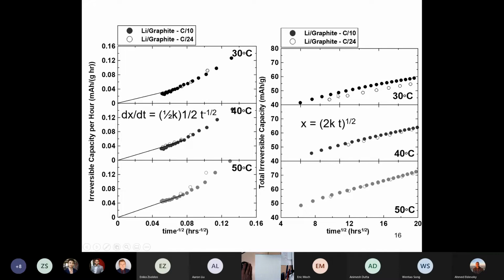So on the right-hand side of this graph, here we plot the total irreversible capacity. Well, the total irreversible capacity should be proportional to the SEI thickness, right? Because all that irreversible capacity is being used to make SEI. So the greater the irreversible capacity, the more thickness you should have. And if you plot that, it should be proportional to time to the power half. So if you plot total irreversible capacity versus t^(1/2), you should get a straight line. And you get almost a straight line.